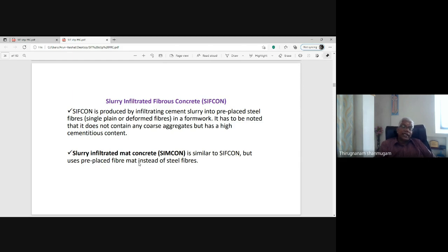Another is slurry infiltrated mat concrete, SIMCON, which is similar to SIFCON but uses a pre-placed fiber mat instead of loose steel fibers. The pre-placed fiber mat is available from the factory, just like a glass fiber mat. You can procure this steel fiber mat, cut it into the required shape and place it in the mold up to the required depth, and then slurry is poured over the pre-placed fiber mat. The resulting product is SIMCON. The performance of SIMCON is superior to the performance of SIFCON.